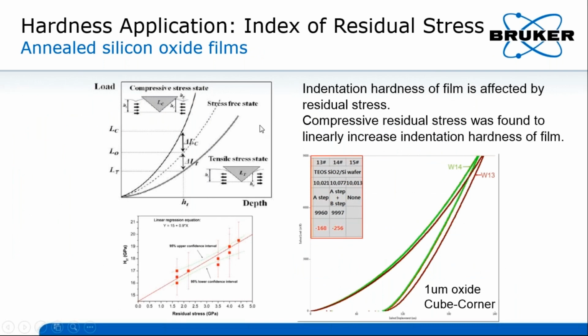Indentation hardness is sensitive to residual stress within the tested sample. Compressive residual stress was found to linearly increase the indentation hardness, and the tensile stress does the opposite. Therefore, indentation hardness can be used as an index of residual stress.